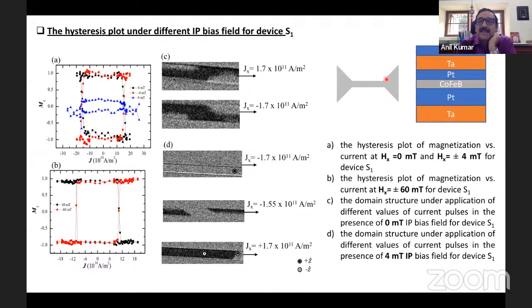And I am making this kind of a hall bar. And now I am applying an electrical current. Now in this particular structure, I am applying an in-plane magnetic field, say 4 millitesla, in plane. And I plot exactly the same curve as I showed you earlier. I get a critical current density here.